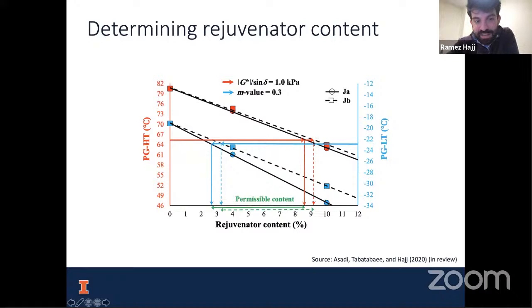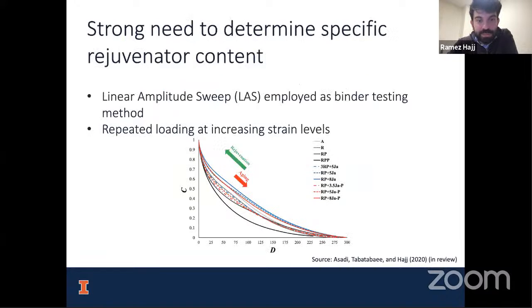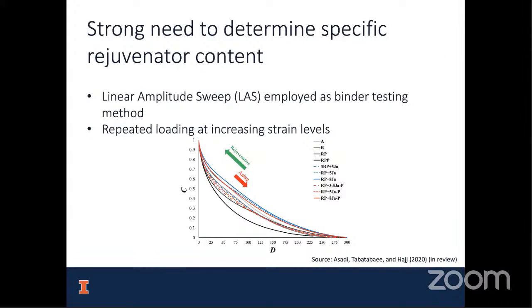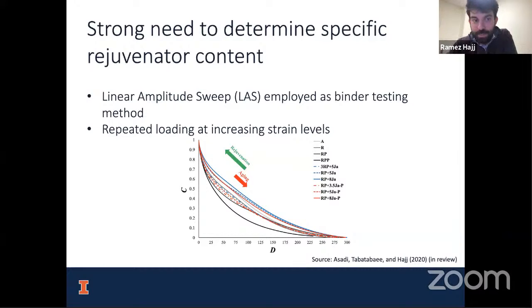So if you can still maintain your same binder grade in this wide range, what you end up noticing quickly is that you don't have a good idea of how much to use. Should you use 3%? Should you use 9% of the rejuvenator? So we developed a system based on the linear amplitude sweep binder testing method. The idea here is that it's a fatigue test. Here we are checking the fatigue life of the binder from many different perspectives.